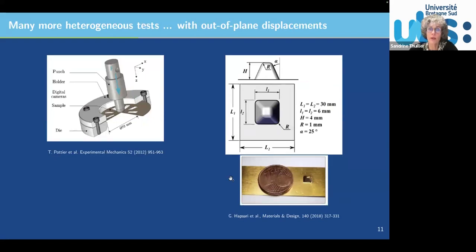And the previous ones were mainly in-plane displacements, but you can also find some out-of-plane tests. I would say this one seems to be typically inspired by the forming process. So you've got a circular blank and tools like in forming. By moving this tool in this direction, you will have mechanical deformation, and it is out-of-plane displacement. In this case, they use incremental sheet forming, directly the forming test, in order to identify the material parameters.